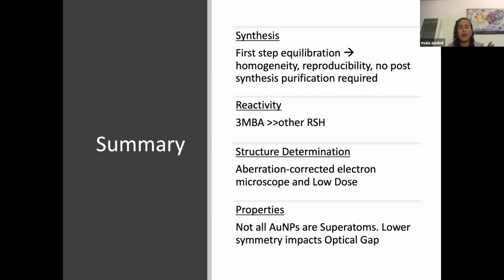And I mentioned this thing of the optical gap because I really like the fact that the structure allows us to understand a property that we didn't know how to explain before. How was it possible that a cluster with 68 atoms was conducting much better than what the prediction said? And that has to do with the lack of symmetry. But I hope that the most important thing that you take away today, even though I didn't talk about cryo-electron microscopy, is that cryo-electron microscopy also has the advantage of working together with your sample in order to protect it from beam damage.